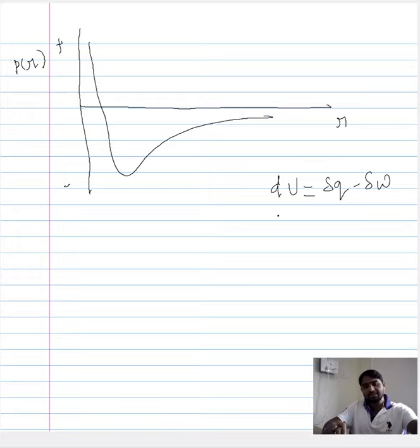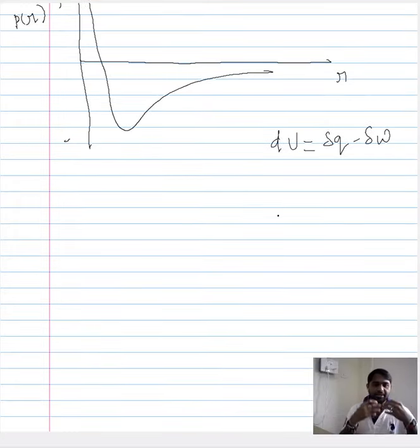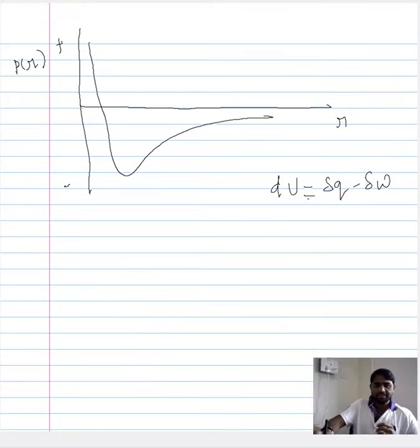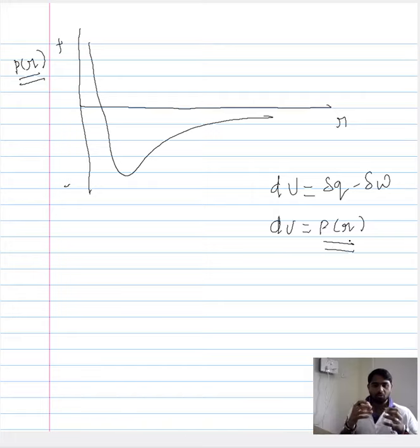Now when your system is at absolute zero, there is no kinetic energy or thermal energy to the atoms, so atoms are sitting in their equilibrium positions. That would mean that the overall internal energy of the system is confined to their positional potential energy, which we have shown here. When we are close to 0 Kelvin, when there is not much vibration and the atoms are confined to their equilibrium positions, the internal energy of the system is fully dependent on the positional potential energy, which results from the interaction between the atoms that we have shown here.